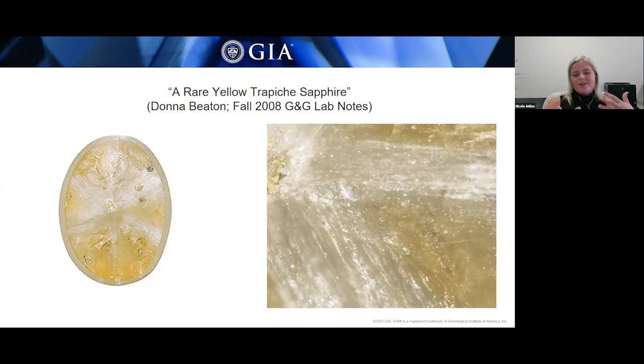While trapiche patterns are well known to occur within emerald, and they have been documented in corundum, they're typically documented in rubies. So the fact that this was yellow was pretty interesting. A small core area that was parallel to the c-axis formed in the center of this formation, and it can be seen in the upper left-hand corner of the photomicrograph on the right.